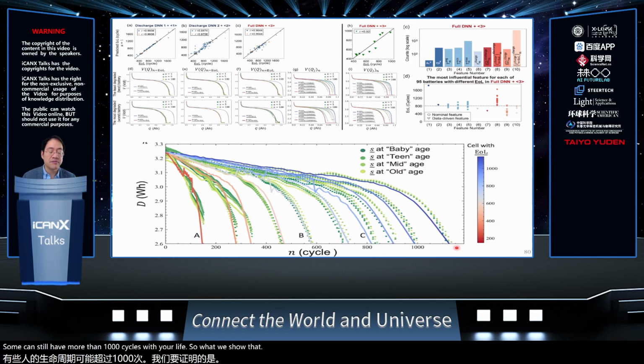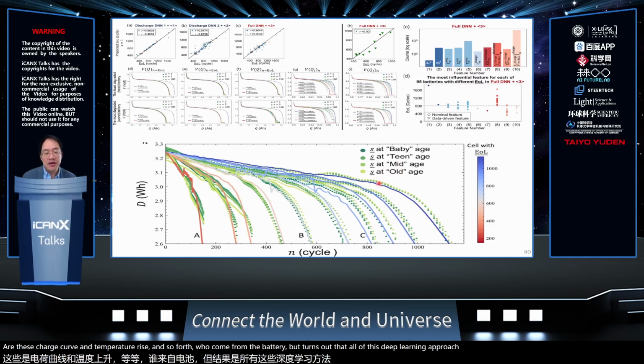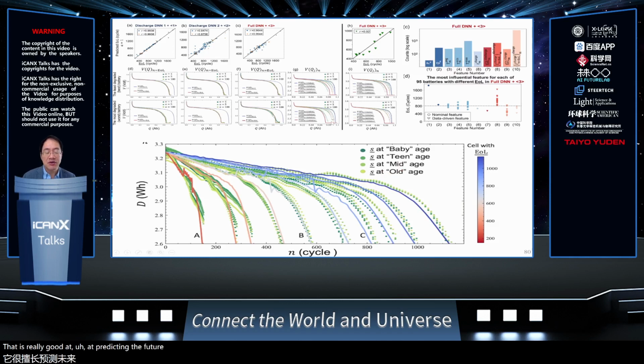So what we show is that just by using one cycle of testing, you can get very good predictions of the residual life, but also, more than the energy density, you can even predict the cycle-by-cycle voltage capacity curves. And this beats the human expert picked features. Human experts have previously used things like battery impedance or the difference between two discharge curves and temperature rise and so forth to characterize the battery. But it turns out that this deep learning approach is really good at predicting the future battery cell performance. And using this, we can reuse old batteries and also build better battery pack systems for load balancing.